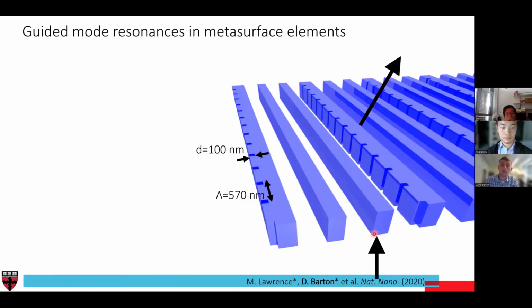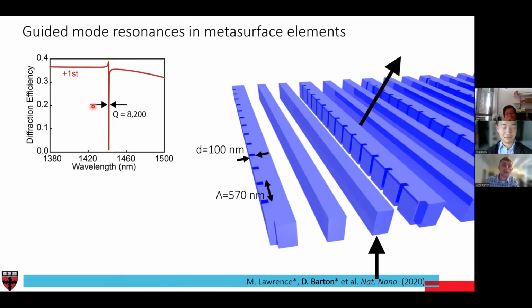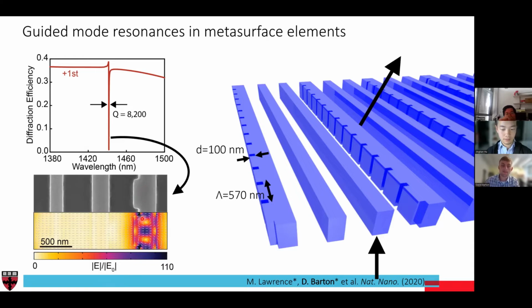And so when we send light in from the bottom, we find there's a narrow resonance that opens up in our diffraction spectrum, or beam steering spectrum, that corresponds to this guided mode in these nanobars. If we look at that particular wavelength, we can simulate what this looks like. We've formed a guided mode resonance in these metasurface elements. On this resonance, the local field intensity is dramatically enhanced compared to free space. The local electric field is over 100 times higher than it would be for light just traveling through without this resonance.